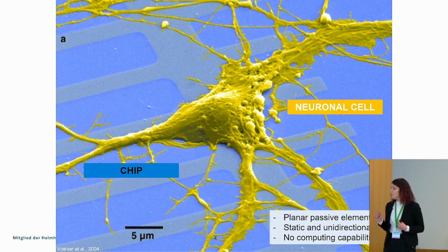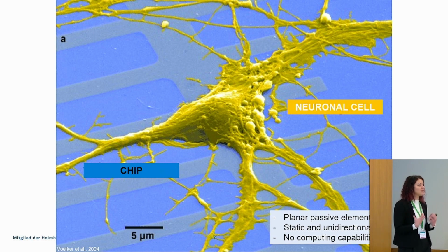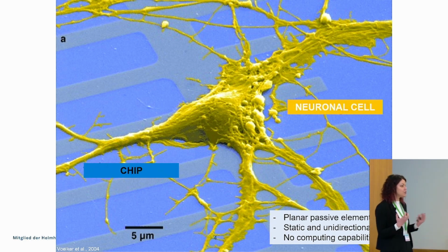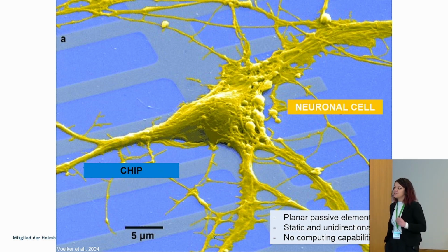But of course, a very important and peculiar feature that they have is their way of interacting with ions and electrons. So they act as intrinsic transducers because they have a mixed ionic-electronic conduction mechanism. Last but not least, we can also engineer these materials to better resemble the stiffness, and actually the softness, of biological matter like the brain. And so we can really achieve low Young's moduli when we, for instance, integrate them in hydrogel-like materials.